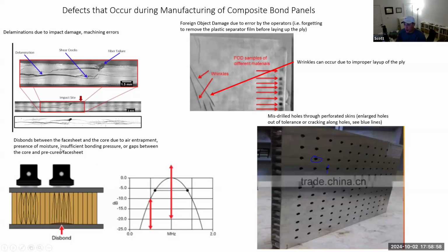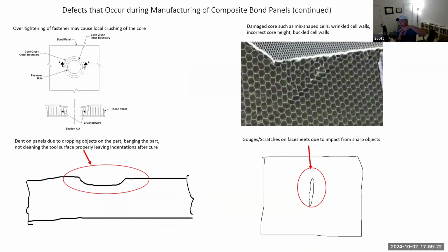Another issue is the bond between the face sheet and the core, due to either air entrapment, presence of moisture, insufficient bonding pressure, or gaps between the core and the pre-cured face sheet. So basically the adhesive is not working here locally and the face sheet is no longer bonded to the core. Other types of defects: if you place a fastener through a honeycomb core and you torque it to preload the joint, if you preload it too much, you're going to crush the core. The core itself is very flimsy, so it could have misshaped cells, wrinkled cell walls, incorrect core height, buckled cell walls, as you see here.